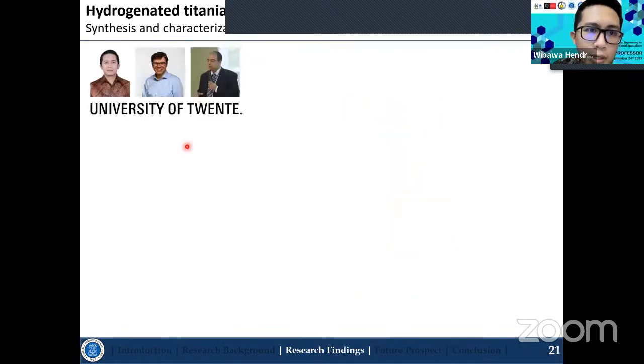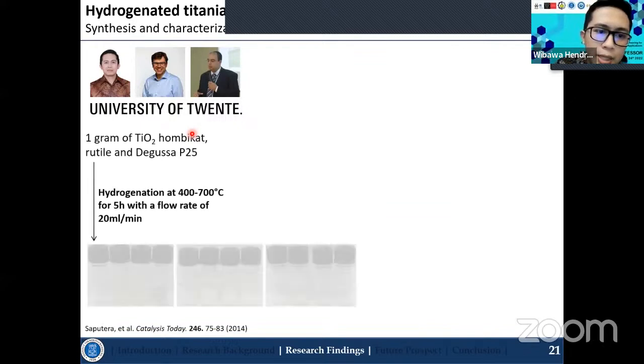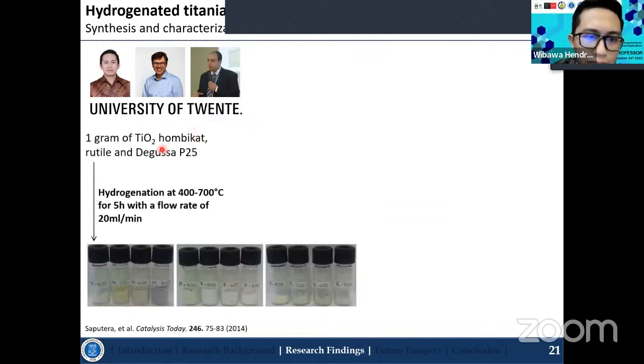And move on to the next one, which is the hydrogenated titania. So previously we mixed the TiO2 and Ti2O3 to create titanium 3+. So for the second method, I use the commercial TiO2 and just hydrogenate at various temperatures. So I purge the hydrogen and heat it up from 400 to 700 degrees C for 5 hours with a flow rate of 20 mL per minute.